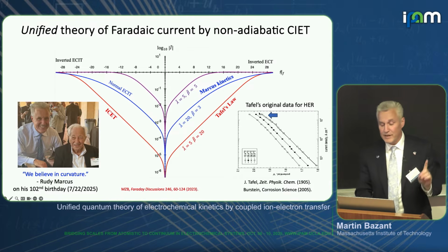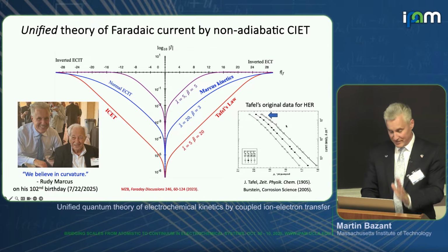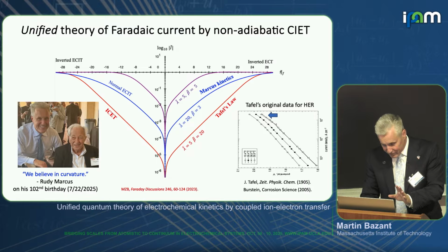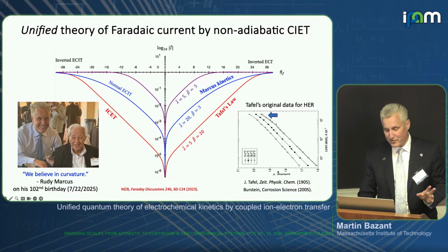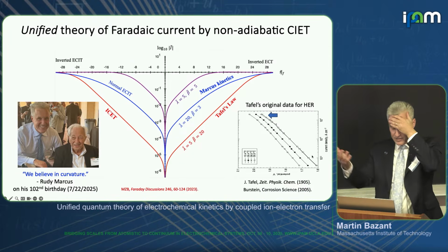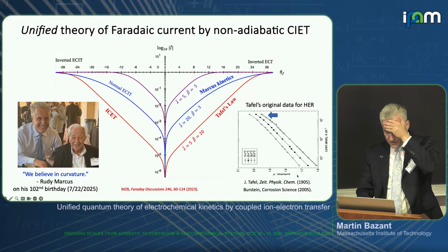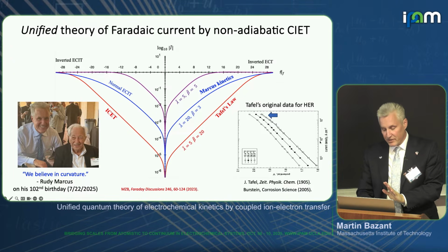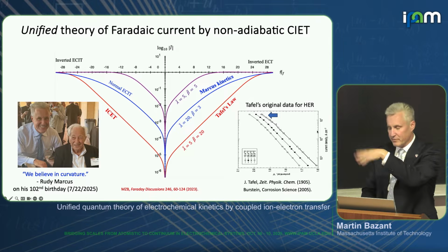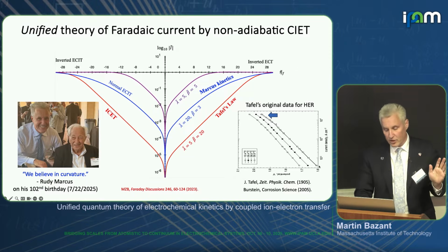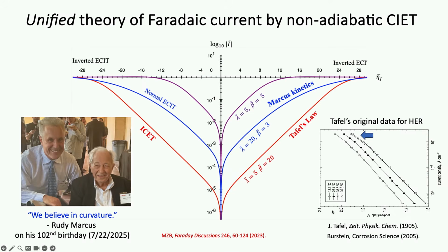And interesting now, let's go back and look at Tafel's data itself. I've flipped it here so it matches my picture, since he actually flipped the 2 axes. What you see here is the replotted data from that other paper I showed you. This is the log of current density versus overpotential for hydrogen evolution in acid. It's pretty straight, his actual data, but it does start to curve.